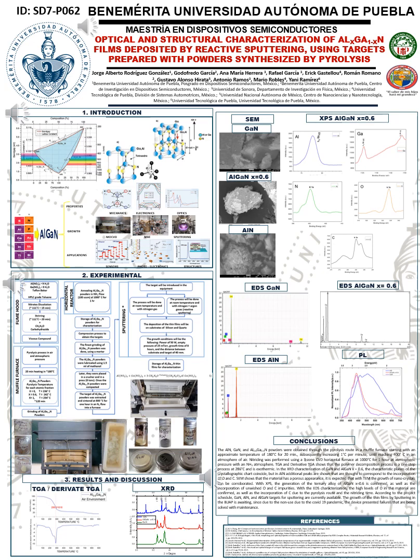Industrially, the production of AlGaN films by sputtering is done using different sources, such as gallium oxide, which is used as a gallium target, aluminum, ammonia, and nitrogen. On the other hand, only AlN or GaN targets can be found on the market, but in particular, the AlGaN alloy does not exist commercially. This work presents the obtaining and characterization of AlGaN films by a reactive sputtering technique using targets prepared in the laboratory, where the solid fraction X is 0.6.